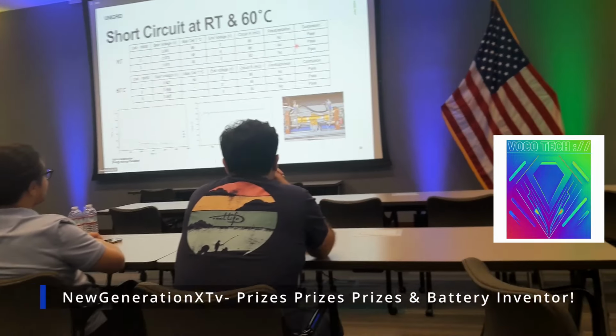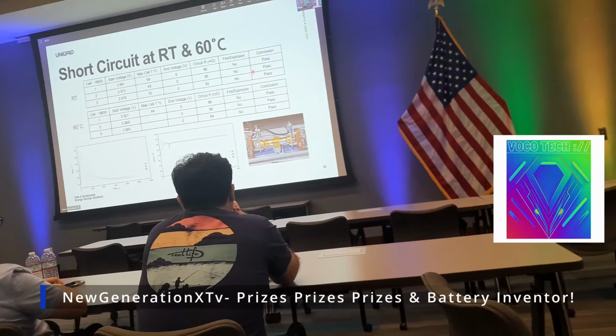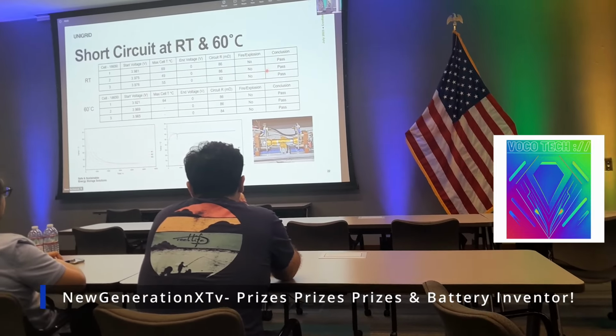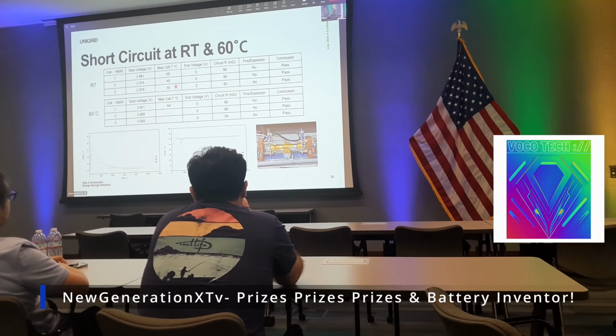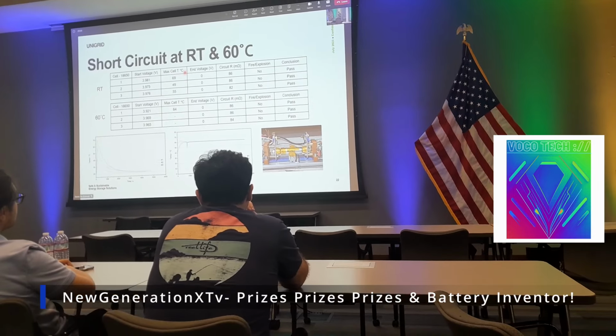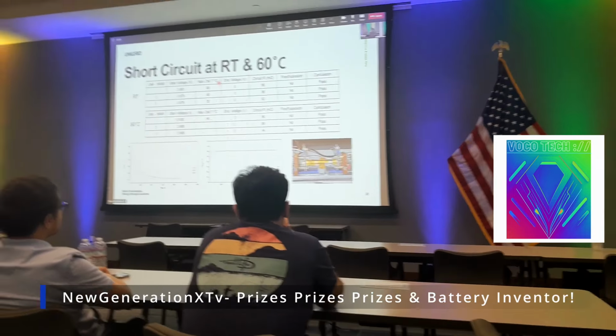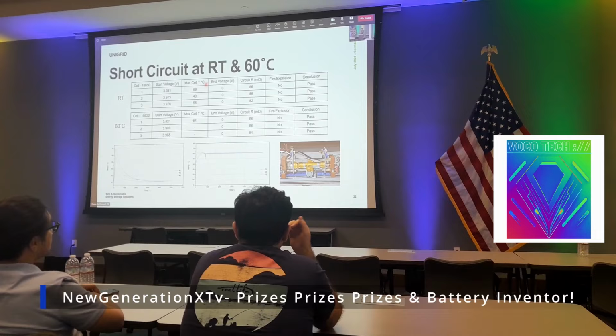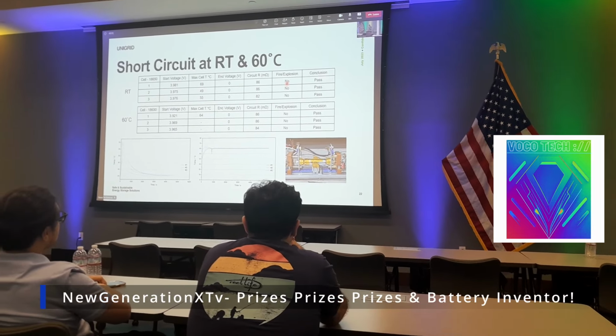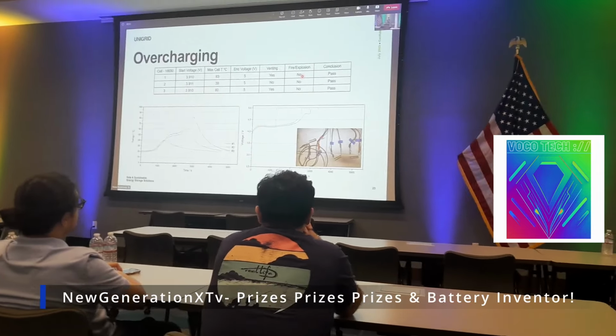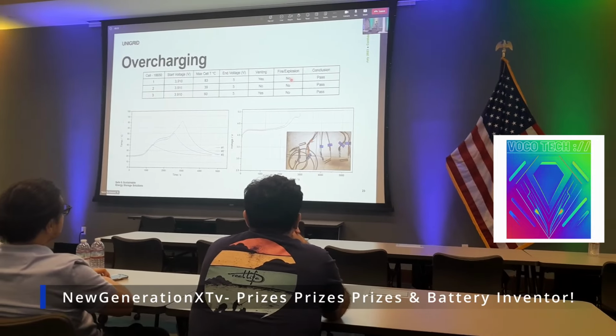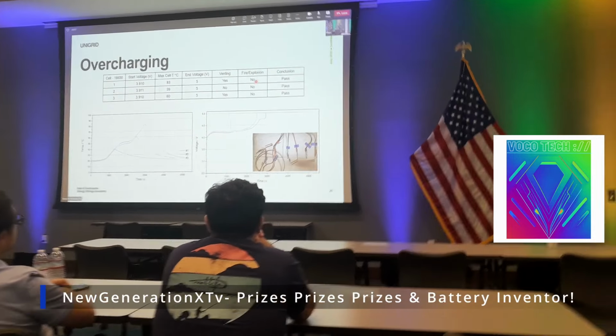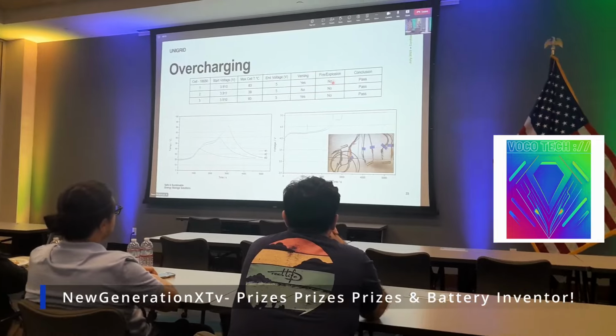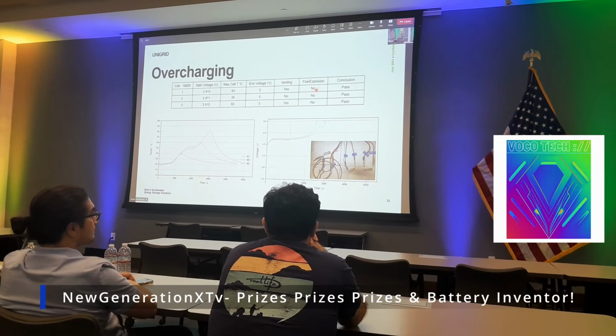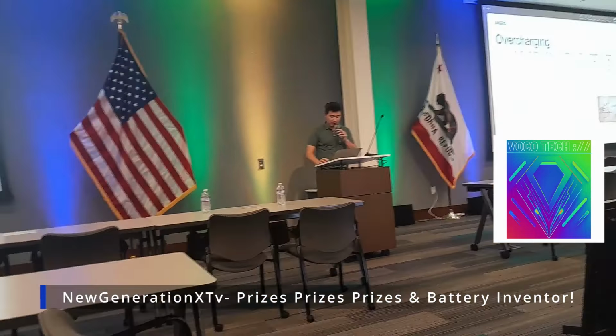Likewise, we also short circuit the battery. We short circuit it at room temperature and at 60 degrees at a fully charged state. Monitor the temperature, it goes up a little bit to about 80 Celsius or so. Sorry, 70 Celsius or so, but no nasty things occur. We also overcharge the battery. Overcharge is one of the common failures for lithium-ion. In sodium-ion, we overcharge it to 5 volts, hold it at 5 volts for 1 hour. Nothing nasty happens. We call it a pass.